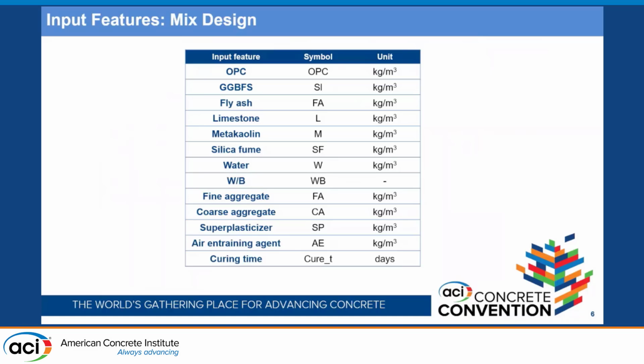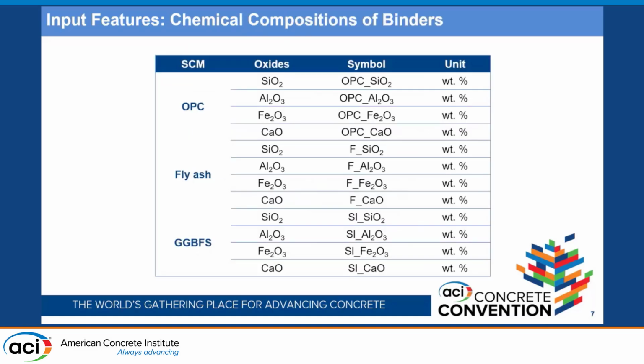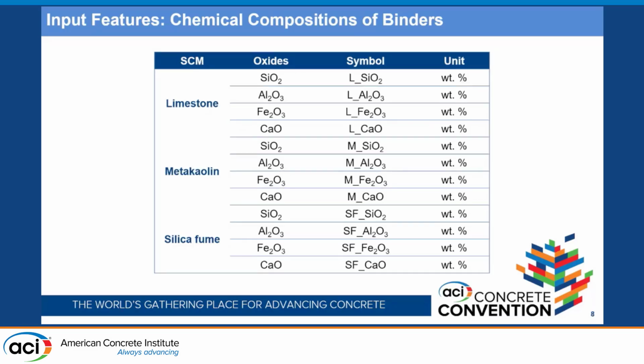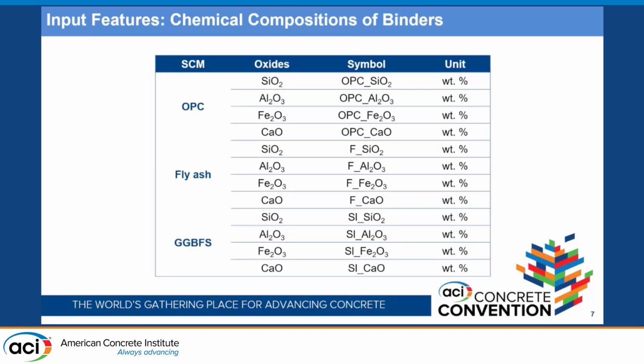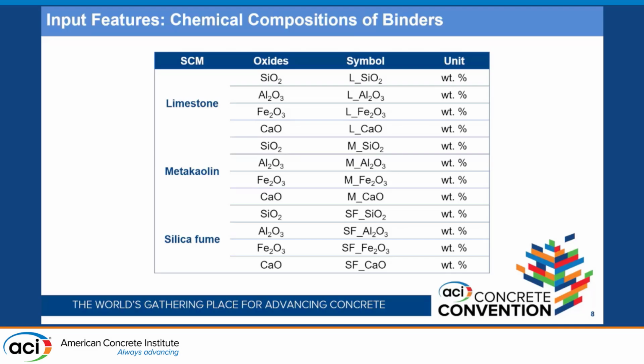Here are the mix design parameters that we try to include in the data set: the cement content, 5 different types of SCMs, GGBFS, fly ash, limestone, metakaolin, and silica fume, the water content, the aggregate contents, the chemical admixtures, and also the curing time and the curing regime in the mixtures. We also try to include the 4 main oxides of the cement and other SCMs used in the concrete mixtures. Here they are for OPC, fly ash, and GGBFS, the silica, aluminum, iron, and calcium oxide contents, and also for limestone, metakaolin, and silica fume.